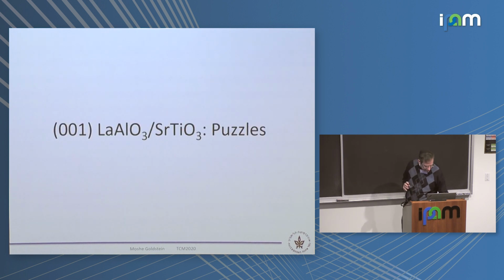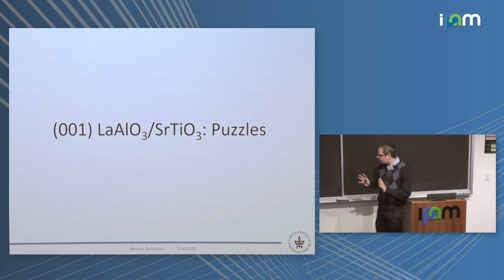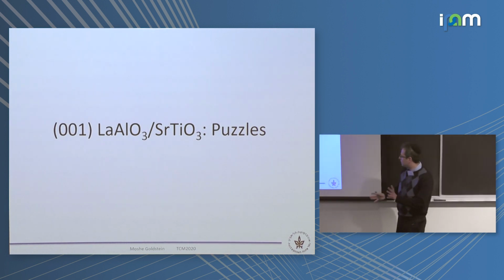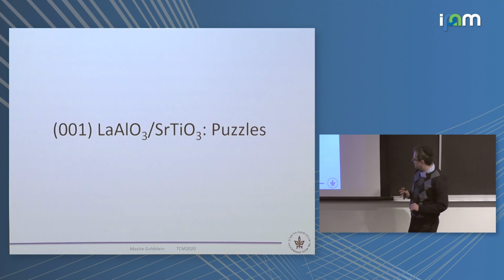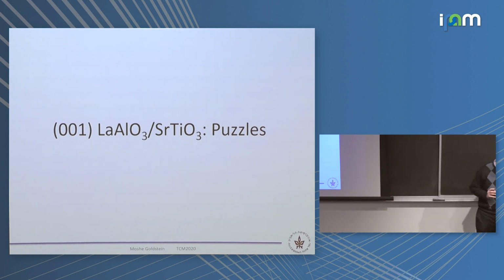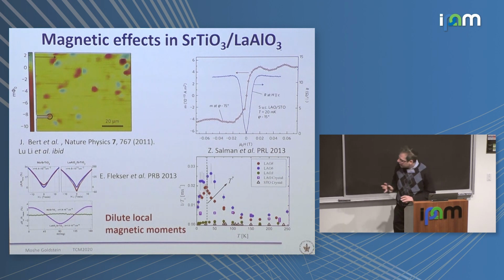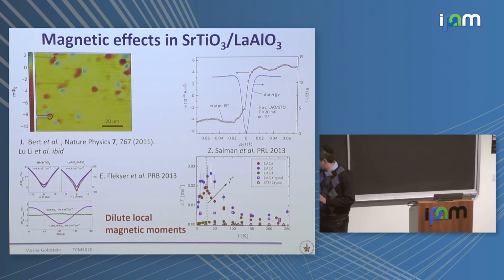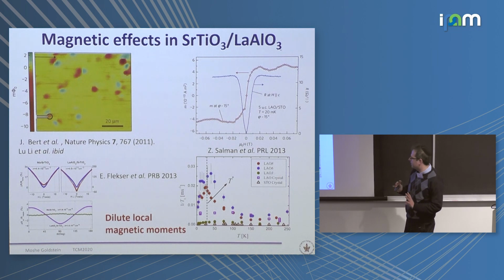I'm going to discuss some other things. So let's try to, okay, so LAO and STO, 2 insulators, the interface becomes conducting. And now let's see that it's more complicated than it seems at first sight. So first of all, let me tell you about the things that are probably not so important. So people have looked into magnetism in this interface, and various things that look like there is some magnetism, but when you do local probe measurements like those ones, and also when you do muon scattering, it seems that there are some permanent magnetic moments, but they are somehow dilutely scattered everywhere.